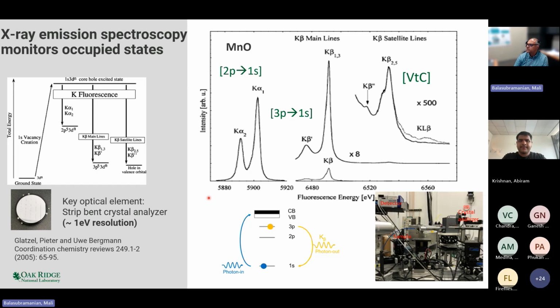And this is sort of like the setup that you would use for it. Your X-rays will come in, it will hit a sample which is here. The X-rays emitted by the sample are then analyzed by a crystal analyzer, which is then detected by a detector. These crystal analyzers can give you energy resolutions of the order of 1 eV or lower, and so you can measure these spectra with good fidelity.